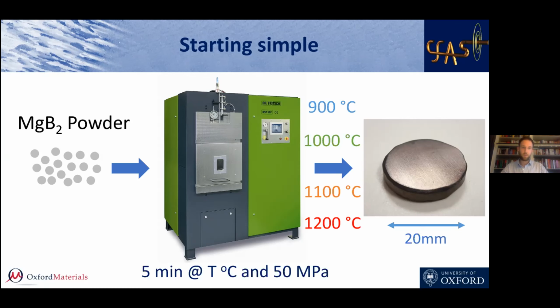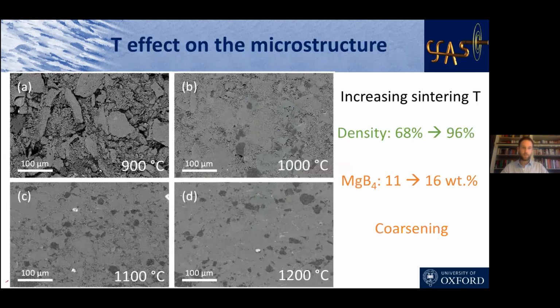So the first thing we realized when we sintered is that it had a big effect on the microstructure. As we increase the temperature, we go from a kind of loose stack of powder, which is barely sintered, to, for 1200 degrees, a solid material, which has very little porosity. And by increasing the temperature, we had a huge effect on density, which increased from 68% for the 900 sample to almost 96% for the 1200. So that was an advantage of the sintering temperature.